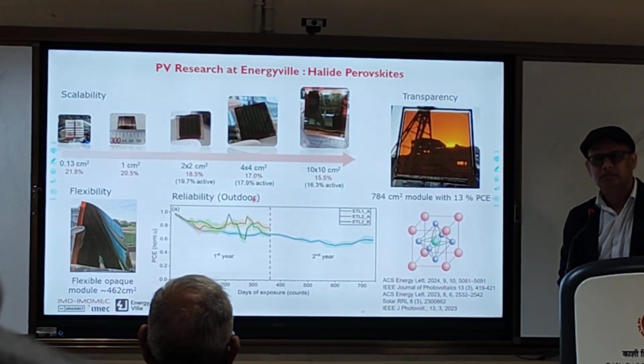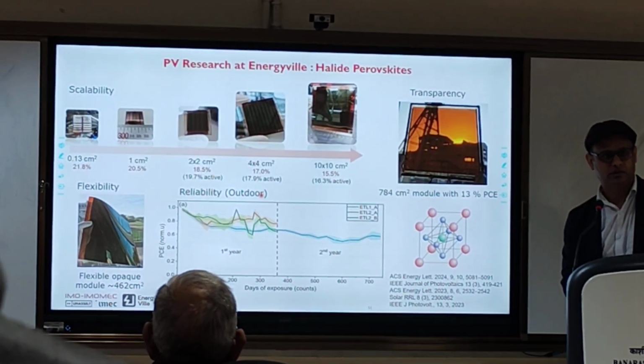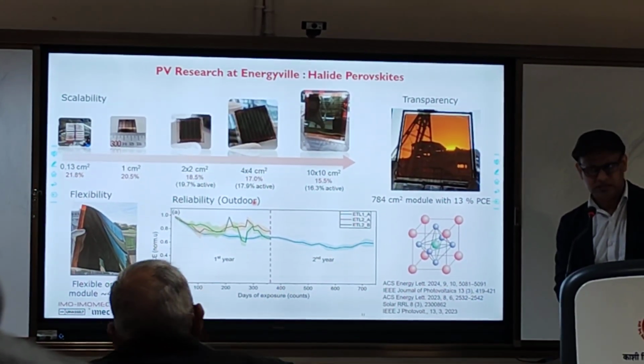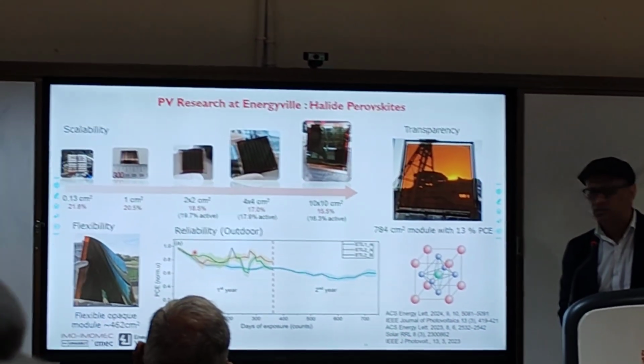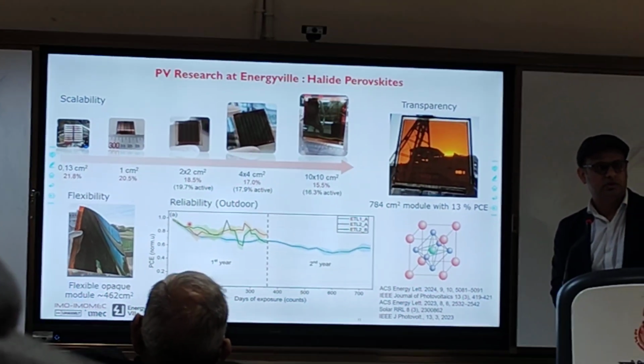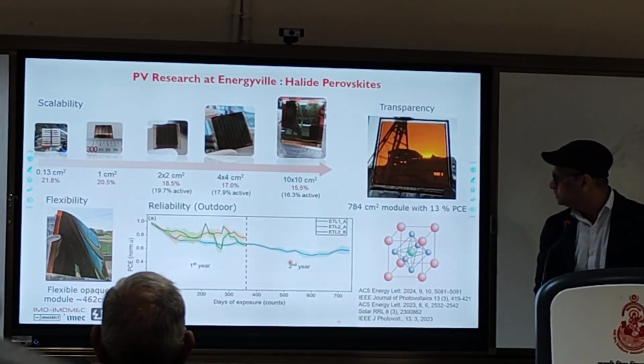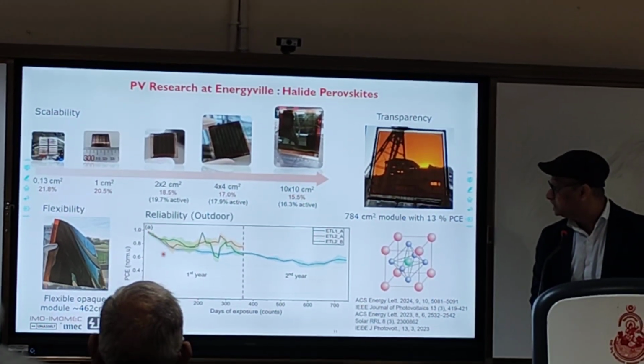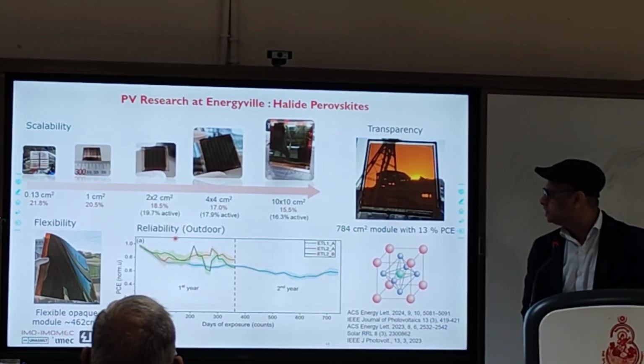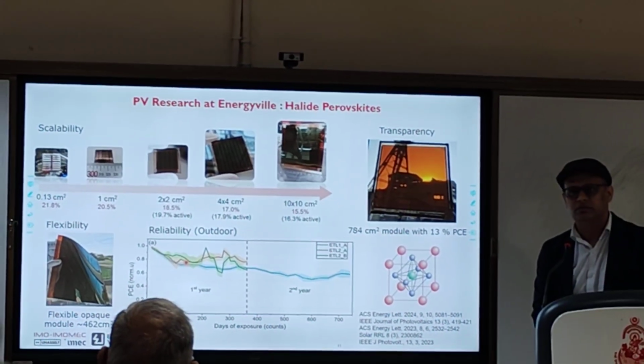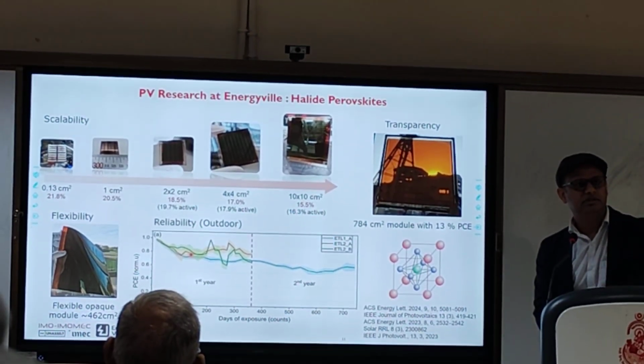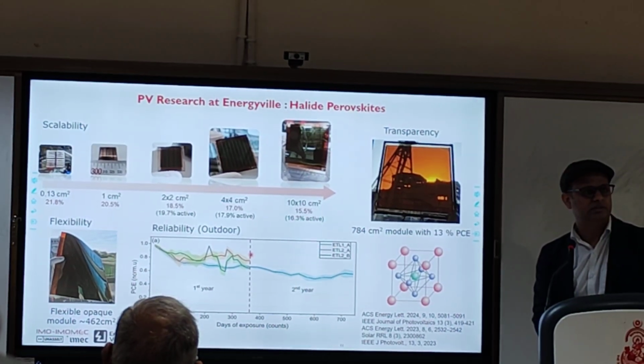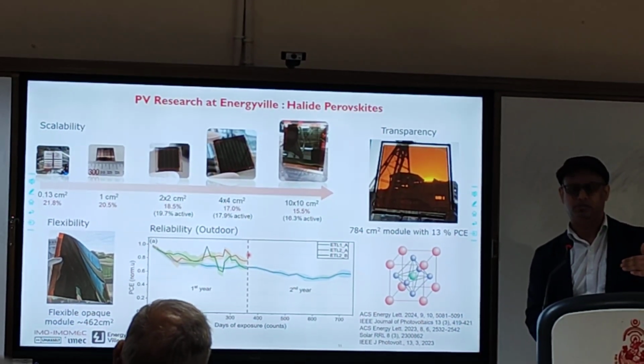There was some skepticism in the community that perovskite cells are not so stable, which is to a certain extent true, but it was not as bad as it was thought to be. You can see that 2 years of data indicates that these cells do not die. They just lose like 20 or 30% of their original efficiency, but they survive more or less. The key is that you have to passivate them and encapsulate them nicely.